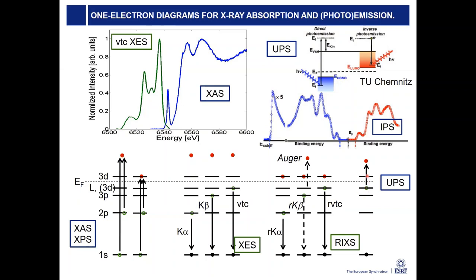This is particularly interesting if you go here to the right and photoexcite an electron from the occupied valence orbital, and then measure the kinetic energy. Then you get the spectrum here. So that could be photoelectron spectroscopy of your valence shell. You can do this also, of course, of any core level. So that's photoelectron spectroscopy. But following the creation of a core hole vacancy, so you create one 1s or 2p hole, this hole is then filled either from the 2p shell, 3p shell, or from a valence shell. Then you call it K alpha, K beta, or valence to core X-ray emission lines, X-ray emission spectroscopy.